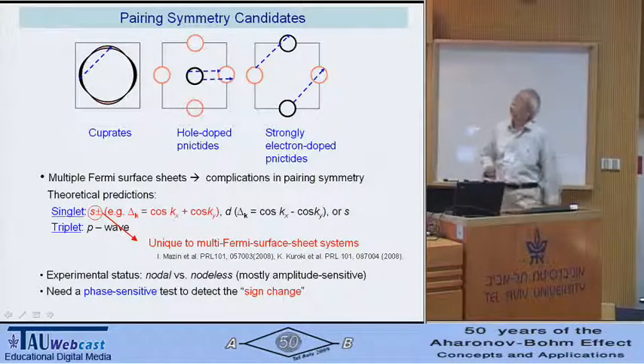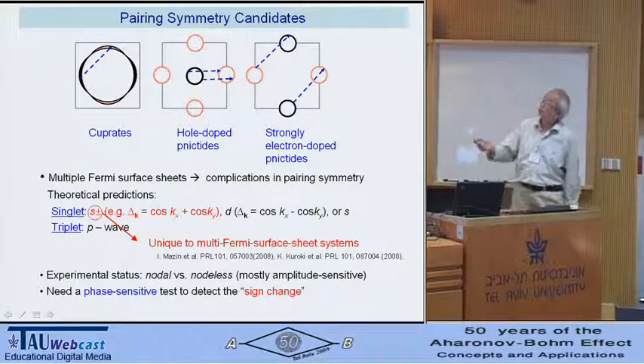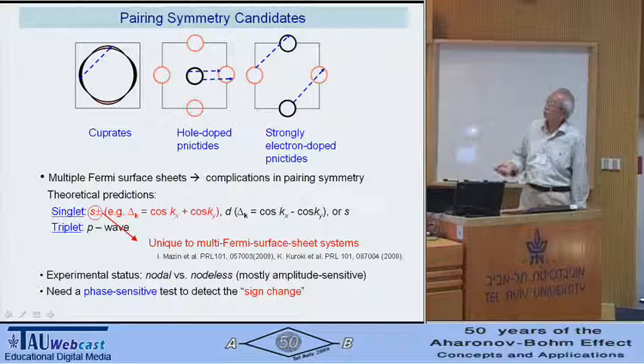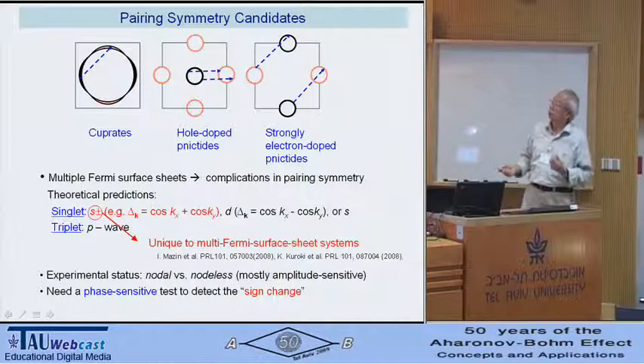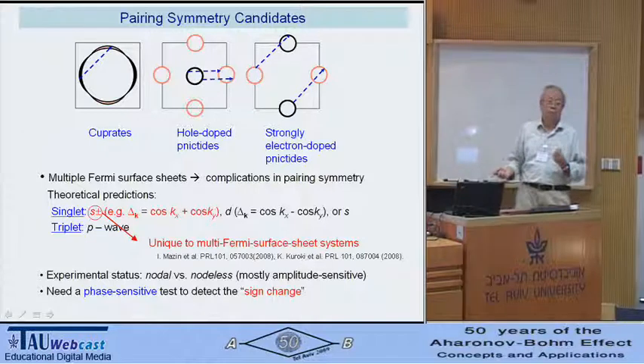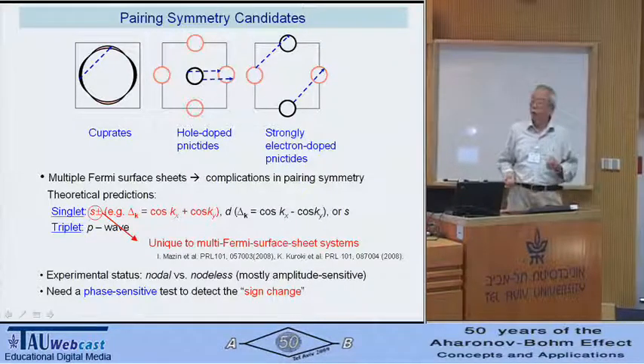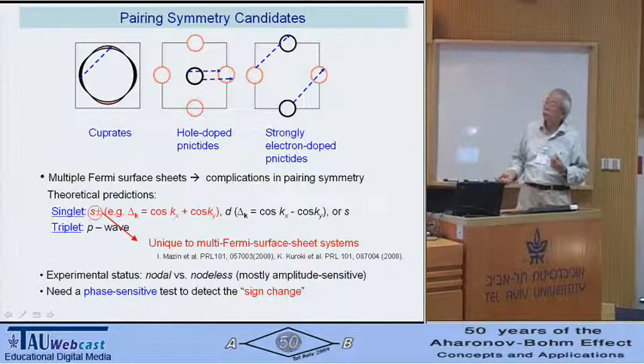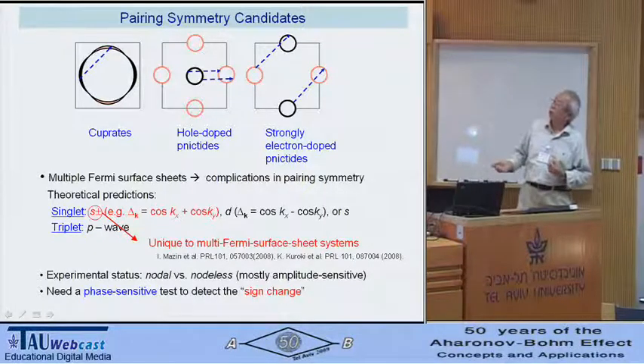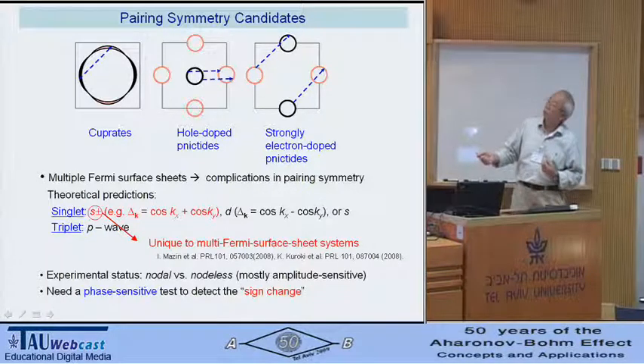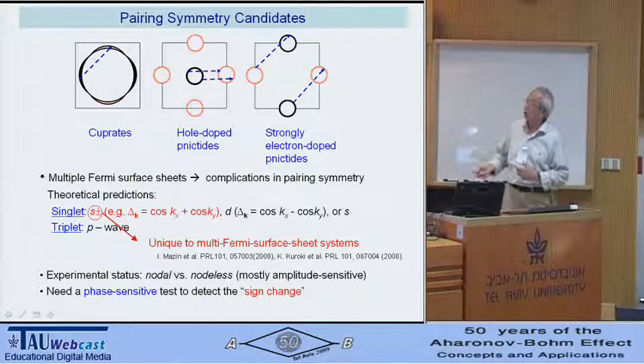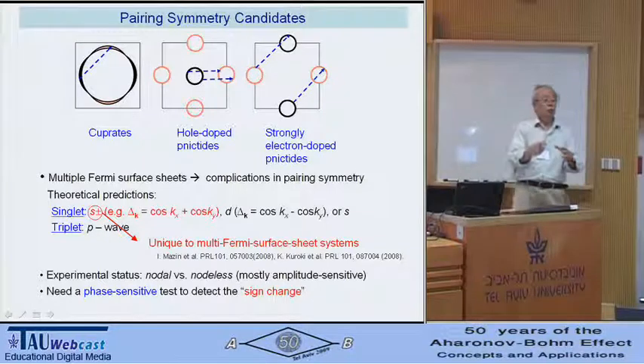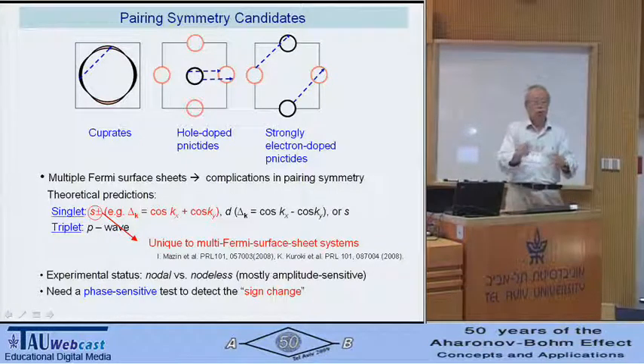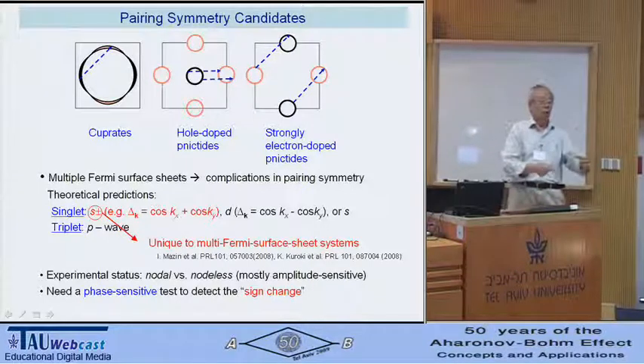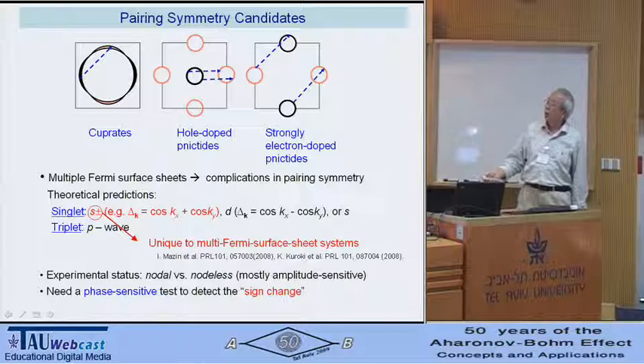And as a result of this, it's very interesting. The Fermi surface is very complicated. Of course, that leads to complication in determining the pair symmetry. Now, the theoretical predictions about the pair symmetry, based on spin fluctuation models, say that it could be s plus minus. In other words, if you have a pair scattering process going like this from one Fermi surface sheet to another, that will give you the so-called s plus minus. In other words, each Fermi surface sheet is an s-wave, but in between those two sheets, it changes sign. So if one is plus, the other one is minus. That's why it's called s plus minus.